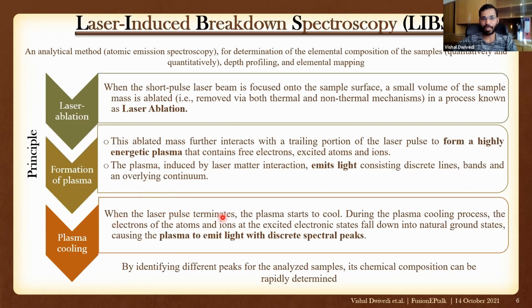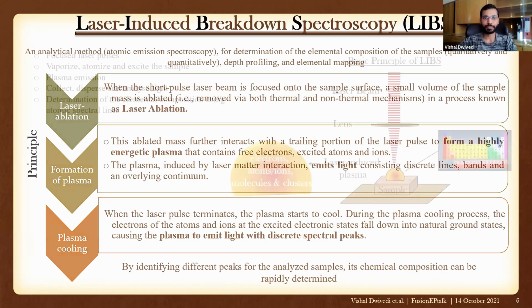When the laser pulse terminates, the plasma starts to cool. During the plasma cooling process, the electrons of the atoms and ions at the excited electronic states fall down into natural ground states, causing the plasma to emit light with discrete spectral peaks and spectral lines. And by identifying these different peaks for the analyzed samples, its chemical composition can be rapidly determined.